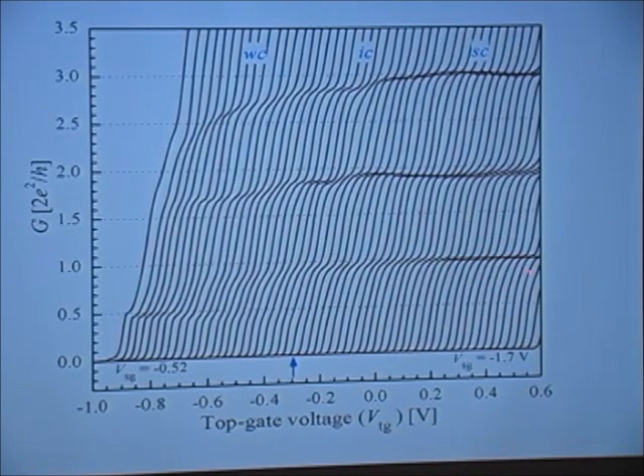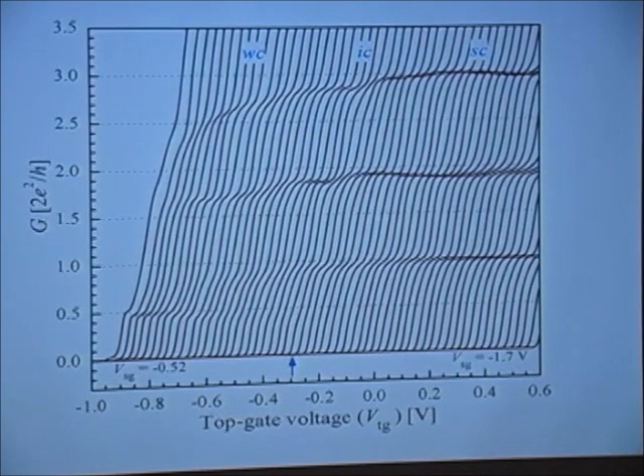But if we don't have a spin, i.e. we abolish spin, they're spinless, we can only get 1 electron in a desired state, and therefore the conductance is no longer 2e squared upon h, but e squared upon h. And what one can do is then go to very low temperatures where kT becomes very small, and then the spin coherence is restored. Although it's very interesting physics, this can be a bit of a problem, because it occurs in the low carrier concentration regime at the same time as we'd like to observe a Wigner lattice. So the two effects become rather mixed up, and one needs to sort them out.